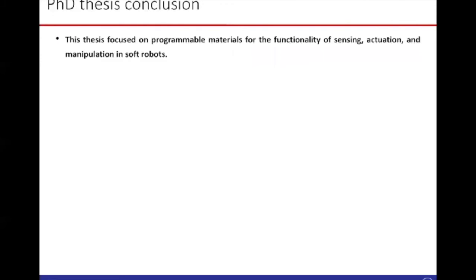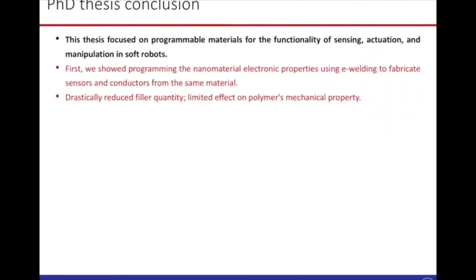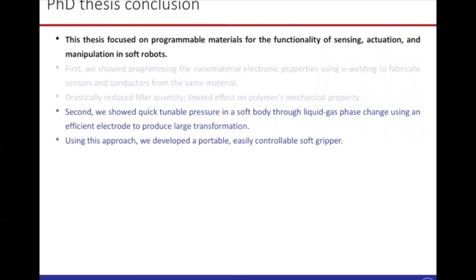Now we conclude the whole thesis work here. This thesis focused on programmable material for the functionality of sensing, actuation, and manipulation in soft robots. First, we showed programming the nanomaterial electronic property using electrical welding to fabricate a sensor and conductor from the same material. By doing so, we drastically reduce the filler quantity, and we believe it has a limited effect on the polymer's mechanical property. In the second part, we showed a quick pressure change in a soft body through liquid gas phase change using an efficient electrode to produce large transformation.